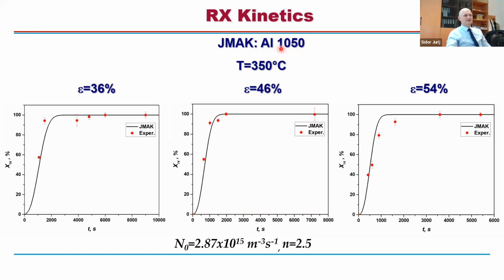And then in our investigation of the 1050 alloy, we worked with it because it's technically pure aluminum. We wanted to work with an idealized system. So recrystallization at 350 centigrade, after various straining levels: 36%, 46%, and 54% thickness reduction by rolling. So we calculated here and compared with our experimental data, right? And then we set N0, which was fixed for all cases. If you remember, I told you the approximate value was 10 to the power of 15. So for all cases, the ideal parameter was 2.87 times 10 to the power of 15. And then we managed to reproduce this kinetics with n equal to 2.5. That was one model parameter.